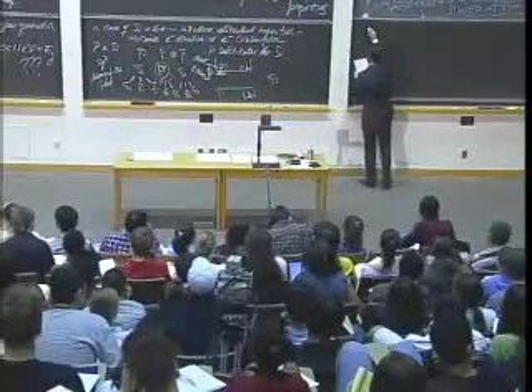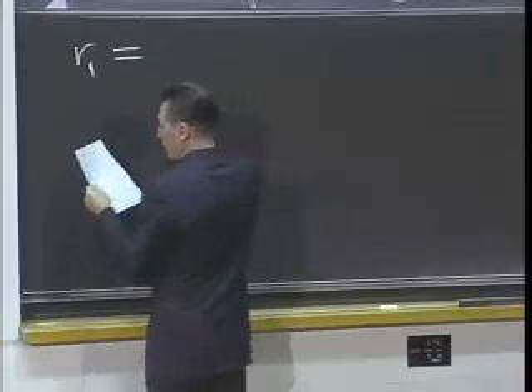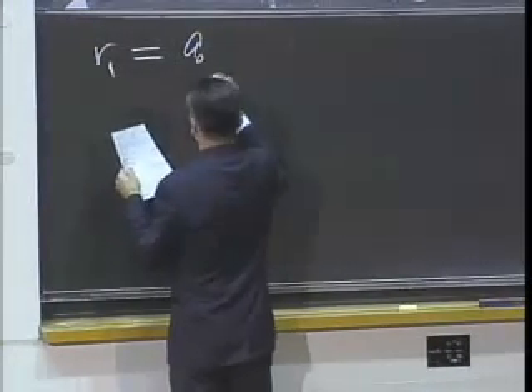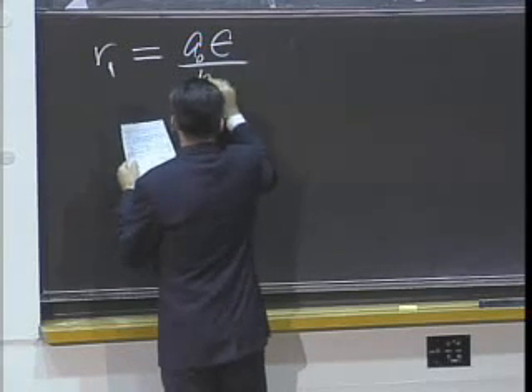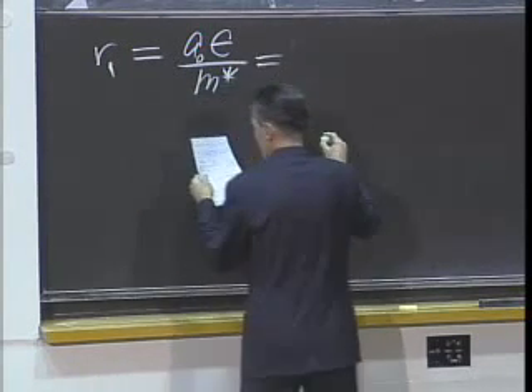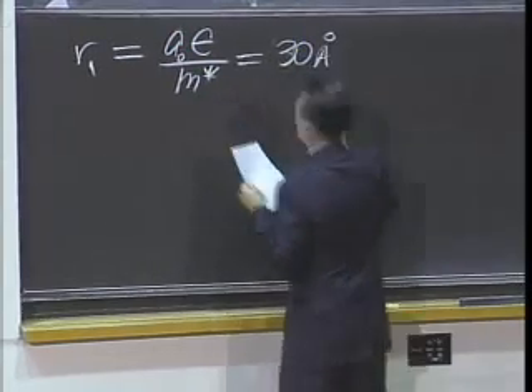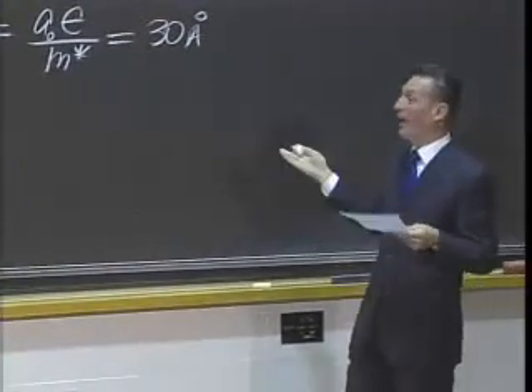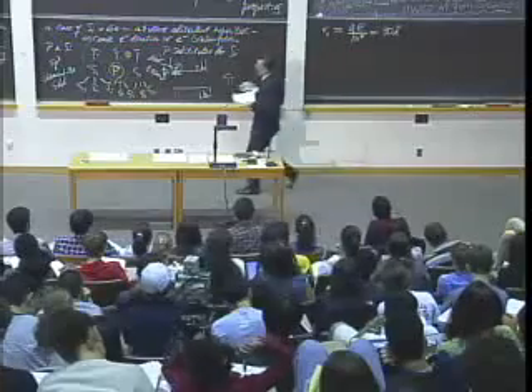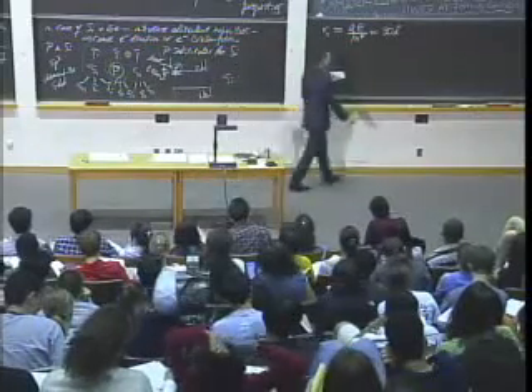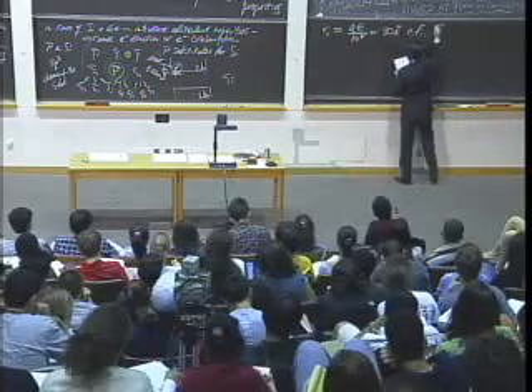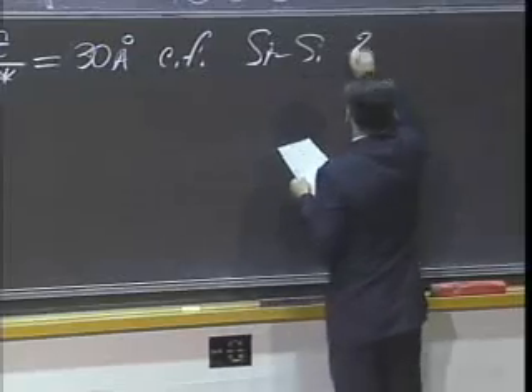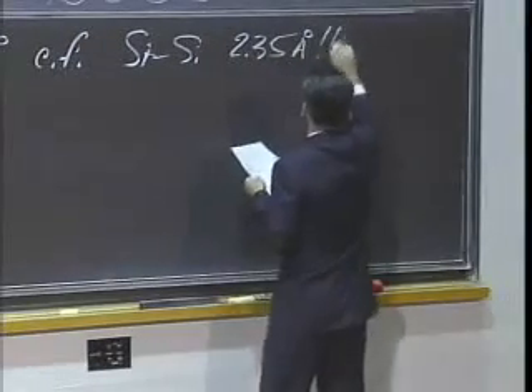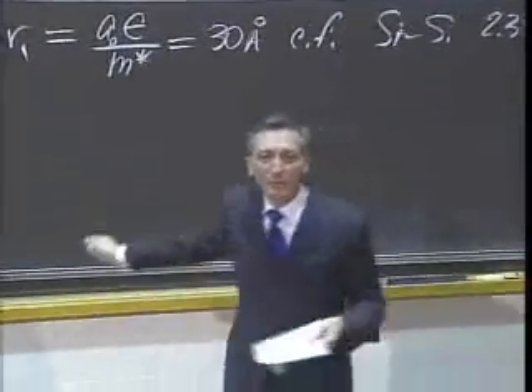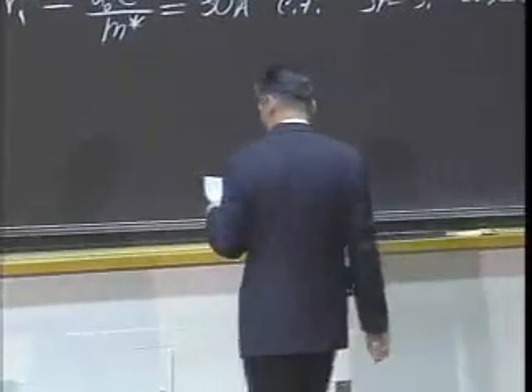So here's what I did. I said, okay, the R1, the radius of this ground state, was going to be given by the Bohr radius times the modified dielectric constant divided by the modified mass. And when you plug in the numbers, you get 30 angstroms. We say, well, I don't know what the silicon-silicon distance is. Well, what do you think it is? You know it's got to be on the order of a couple of angstroms. So if you compare that, the silicon-silicon distance is 2.35 angstroms. So this electron's way, way zooming around. So, fantastic what we've learned here.